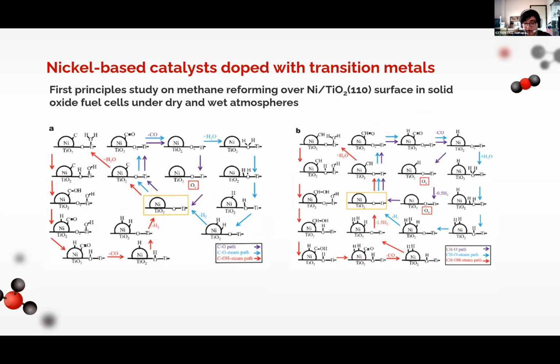And then is the use of nickel-based catalyst doped with a transition metal. This paper studies the mechanism of the reforming reaction on the surface of nickel titanium oxide catalyst in a humid environment. During the reaction, two phenomena could be seen: the migration of oxygen ions inside titanium oxide and the existence of lattice oxygen at the interface of titanium oxide.